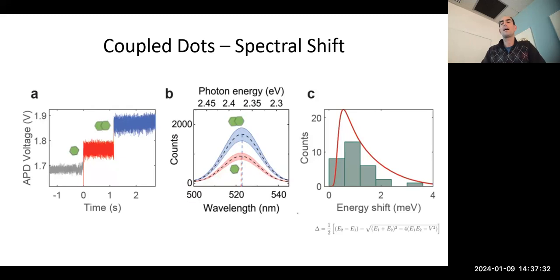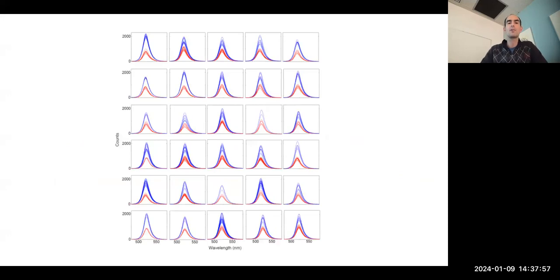Assuming you're thermalizing into the lower energy state, the shift of the red shifted state is given by the expression at the bottom. We fit that expression with the observed distribution of shifts from multiple experiments - individual quantum dots, taking spectra on each one when they trapped one and then two, before and after, seeing the shift in each.